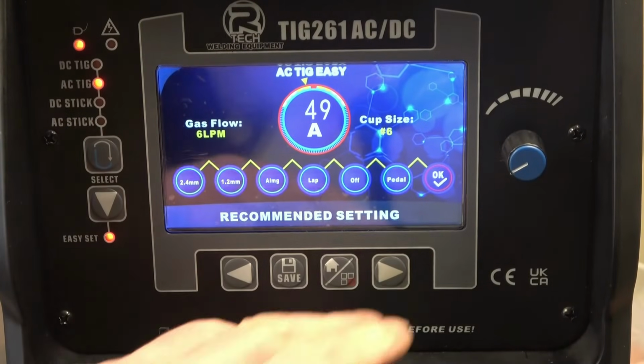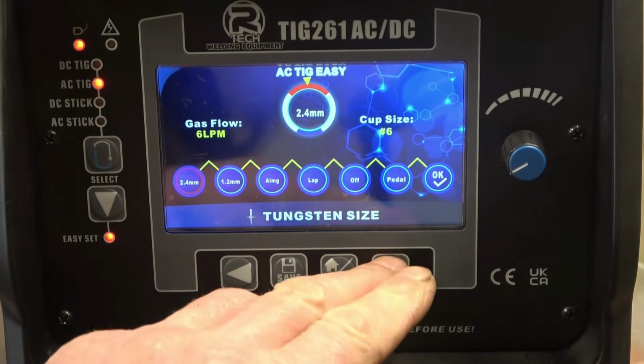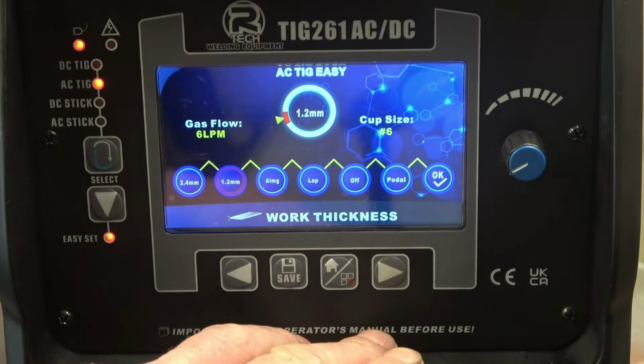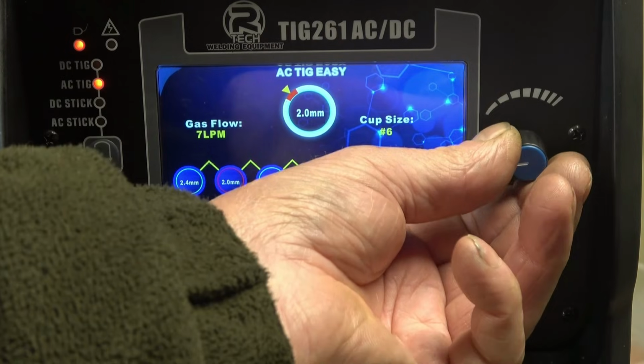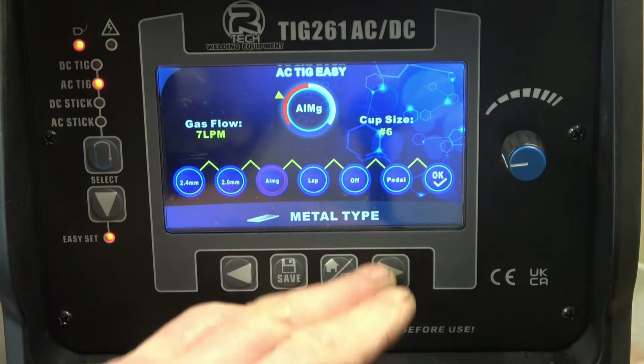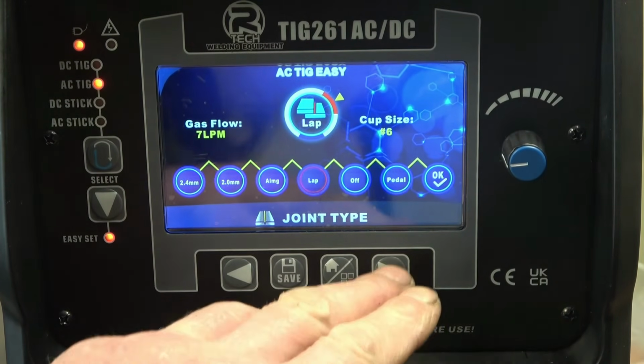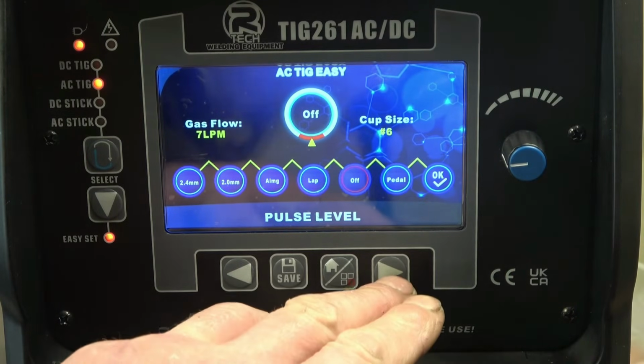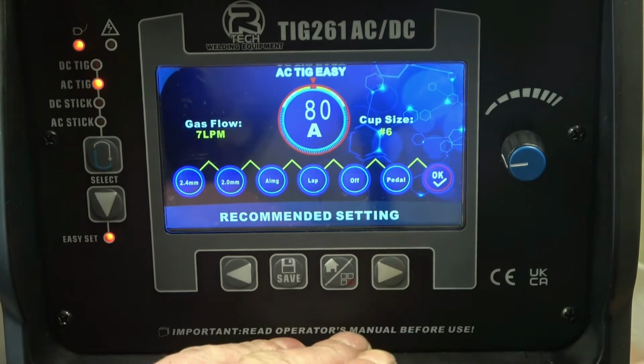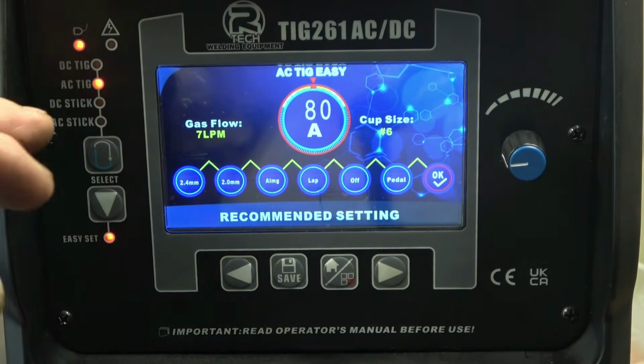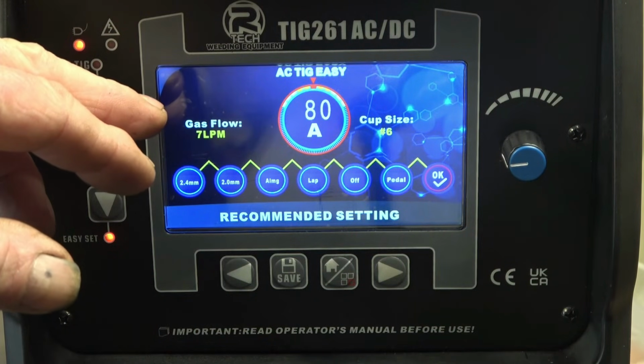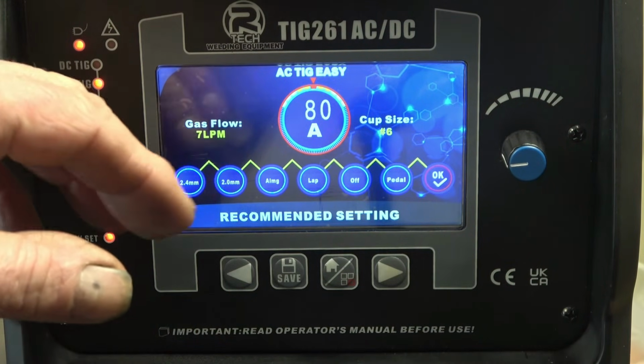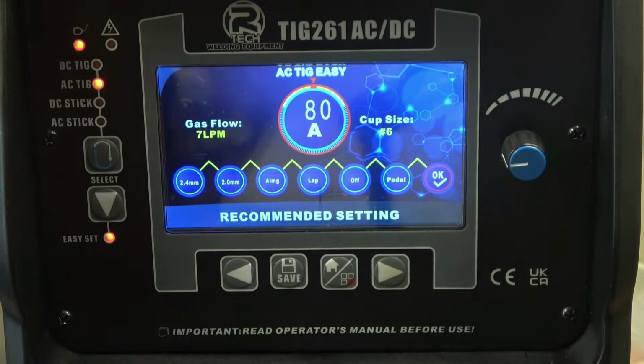Right, that welded very nice indeed. We'll go up to thickness, same tungsten. Going to go up to 2mm. Magnesium based alloy. We'll do a lap joint again. Pulses off on a pedal. Okay. So now we've gone up to 7 litres per minute gas flow. Going to give us 80 amp starting point, number 6 cup.